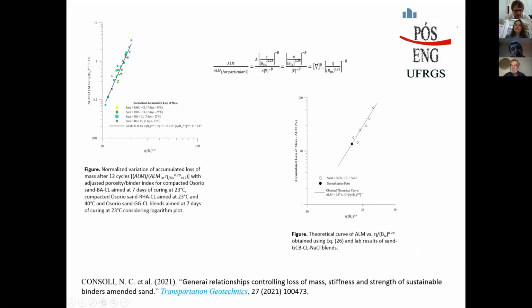And finally, this is a paper that was just published in Transportation Geotechnics, showing that we have plenty of other resources to improve any kind of soil, like rice husk ash, as I showed you before, ground glass, bottom ash, and of course fly ash and others. And we show that this index versus the accumulated loss of mass, in a normalized way, all of them get to a unique curve, which is shown here.